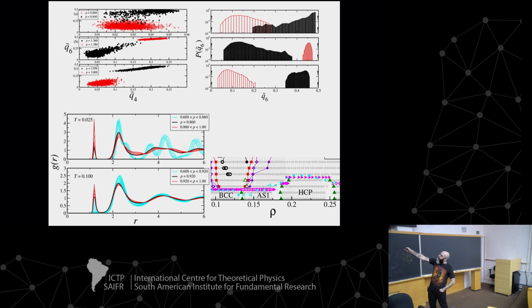So at the low temperature in this transition, we can see that at lower pressure we have the BCC well-ordered phase here in blue. And as I cross the transition at the pressure of 0.86, you can see that these little guys, the first length scales, start to grow, and the system goes to the amorphous state.